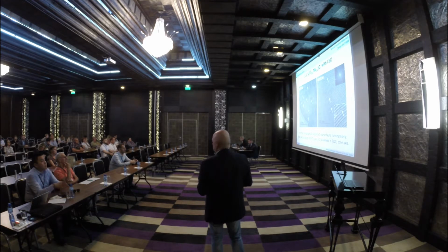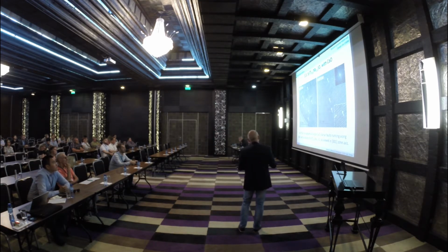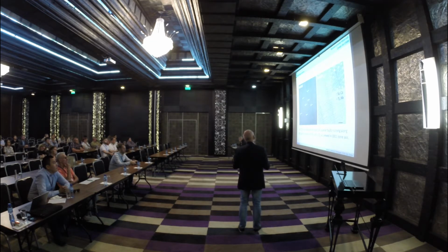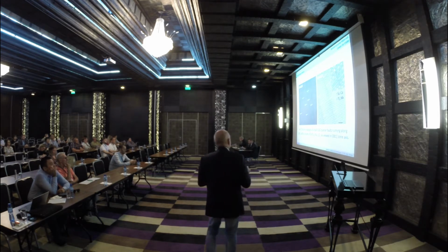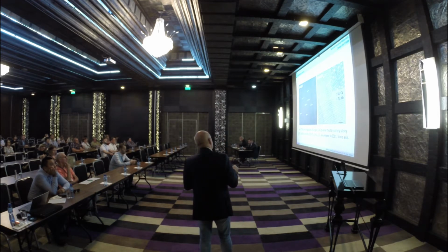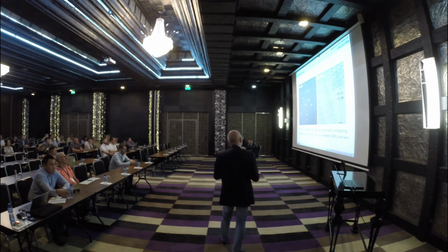However, since calcium oxide is smaller than strontium, it actually forms a lot of three-dimensional loops, like here, which means that we have really 3D orientation of these planar faults. Again, with STEM imaging, we could identify the strontium and calcium mixed columns, and we were interested in whether calcium goes preferentially into the matrix or along the fault.